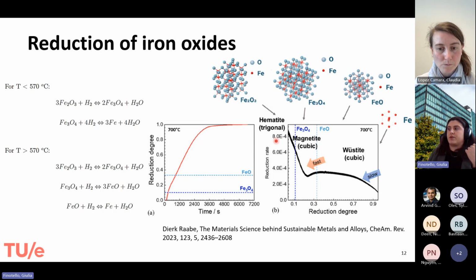If we look at the reduction rate, we also see something interesting, which is that the first steps of the reduction are very fast. So the hematite to magnetite is very fast, but the last step, actually the last 80% of your reduction, is a very slow process. So that is why this reduction can take a longer time.